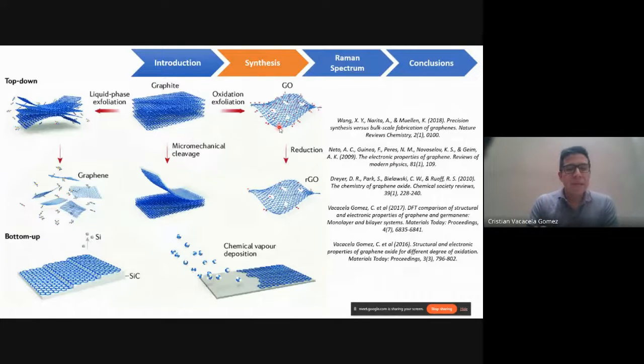When we apply chemical reduction, for example using citric acid, ascorbic acid, or another chemical agent, the idea is to remove these oxygen functional groups in order to get a material very similar to single layer graphene. But also look here: we reduce the presence of oxygen functional groups, but we can also introduce defects, in-plane defects or at the edges. All these defects can be detected and understood in terms of Raman spectroscopy.